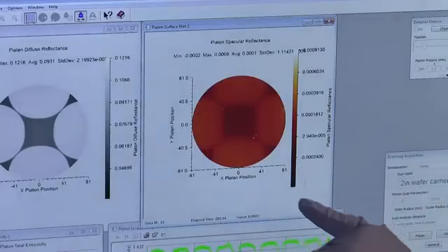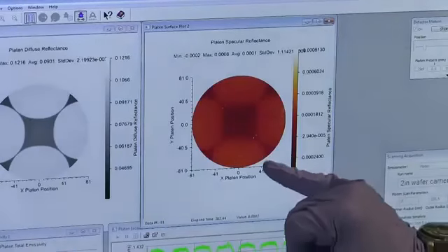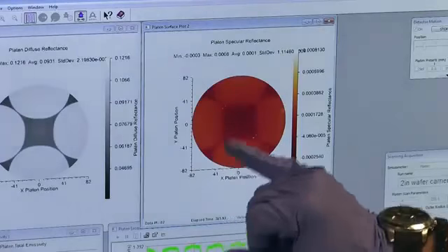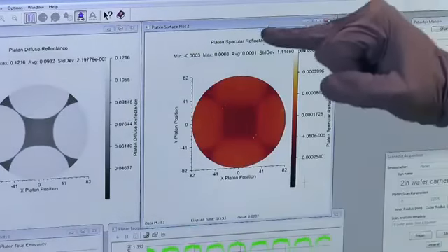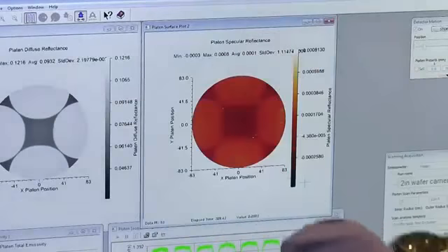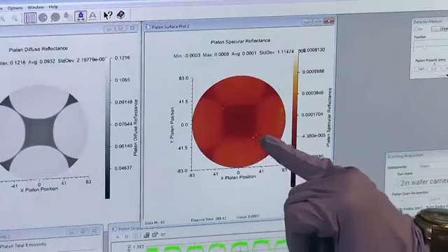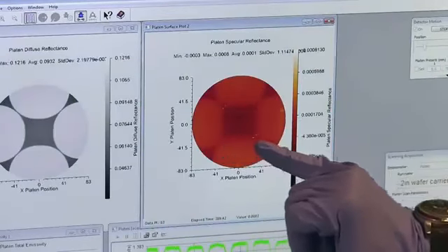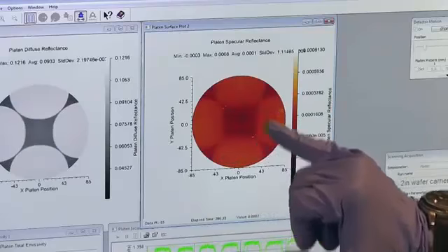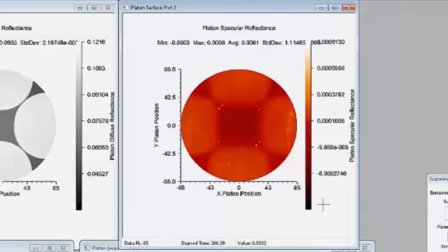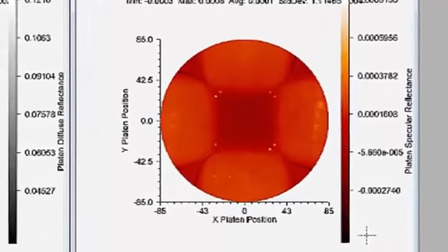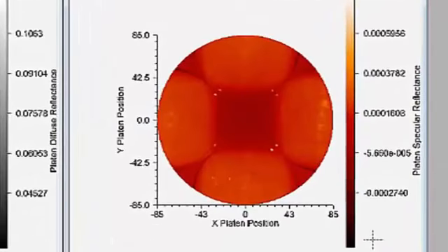So we're about 80 millimeters into this scan, and you can see clearly now the wafer pockets, both in the specular plot and the diffuse plot. If you look closely, you can see these white specks along the pocket edges. Those are actually the pocket clips. It shows you that the specular signal is very sensitive to any surface changes or deformities or scratches.